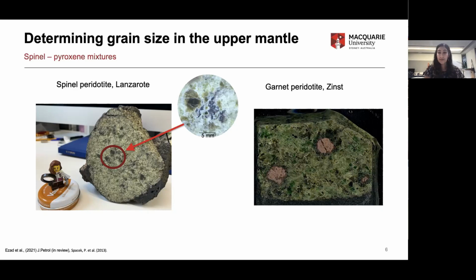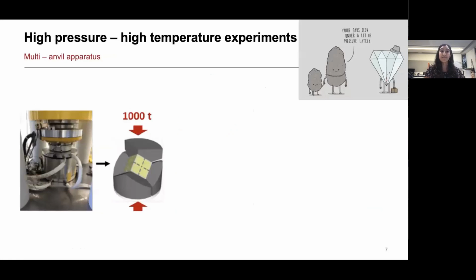Being an experimental petrologist, I turned to the tools of my trade, which was a multi-anvil apparatus. So I did my experiments at University College London, and I used a multi-anvil apparatus. And the picture you can see here on the left is showing what a multi-anvil press looks like. And we often say that these have a hat box geometry because we apply a load or a downward ram force onto the hat, which is the lid of this box here. And the box is where our experiment is contained.